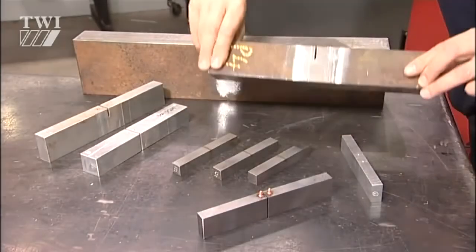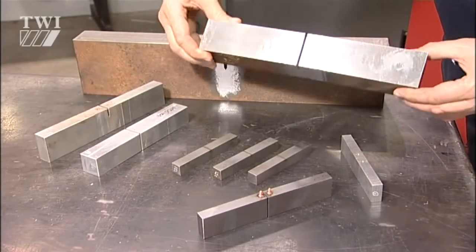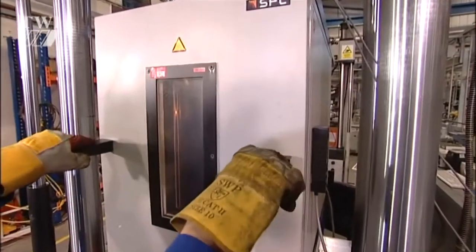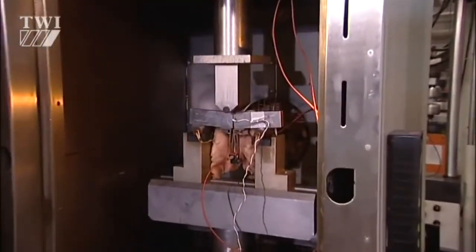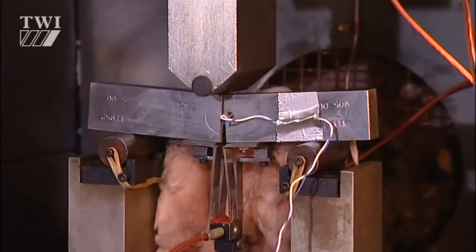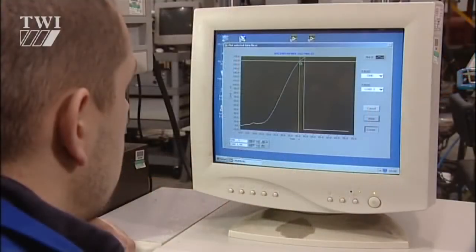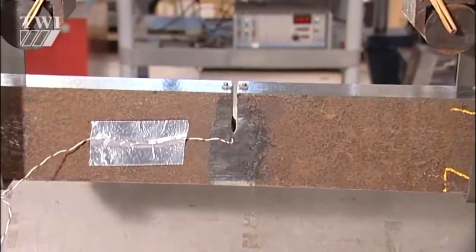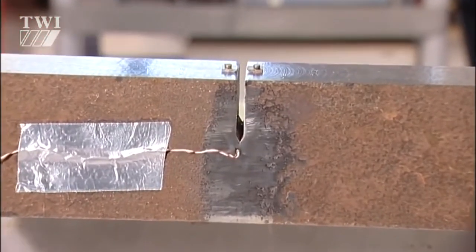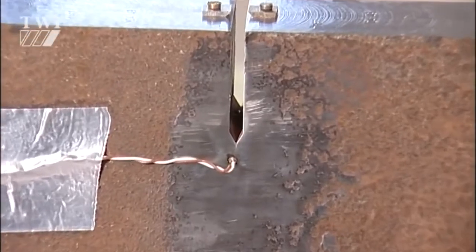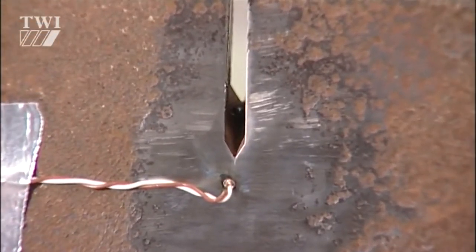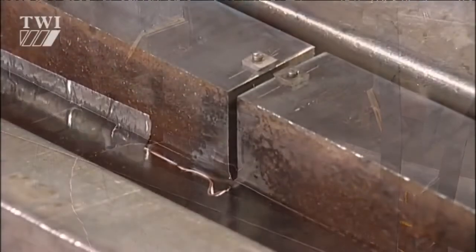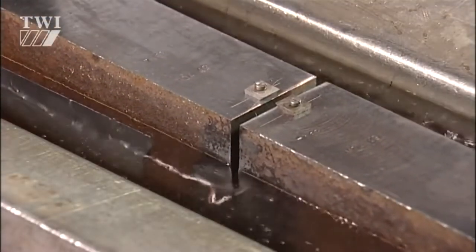Full thickness specimens are used to determine critical conditions in structures subjected to lower rates of loading in another test method, the crack tip opening displacement. CTOD testing, as it's known, has the added advantage of providing quantitative data for use in flaw assessment procedures. This rectangular section specimen features a sharp notch and a small fatigue crack. In other words, a sharp defect. The size of the opening of the slot before fracture is a measure of fracture ductility.